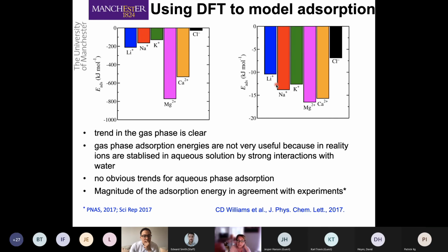However, if you take into account that the ions are very happy in the bulk, because they are hydrated there, and then you perform the DFT calculation with an implicit solvent rather than in vacuum, then you see that the adsorption energies are still negative, so there is still adsorption. But the values are much smaller, and also there is no specific trend with the ions really.